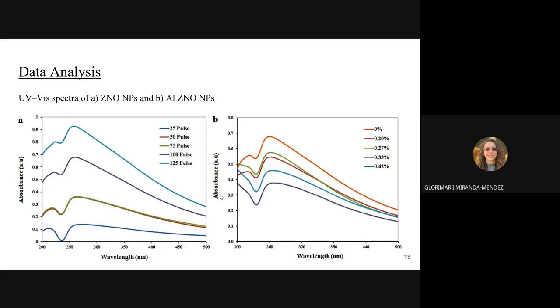With the UV-vis spectra of both the zinc oxide nanoparticles and the doped zinc oxide nanoparticles, they determined that each of the nanoparticles has a peak that centers at 260, both undoped and doped. In particular, the non-doped nanoparticles exhibit a behavior where, with an increasing number of pulses, there's also an increase in the absorbance. This can also be related to the concentration that is generated with the increasing amount of pulses, which results in an increase in signal.